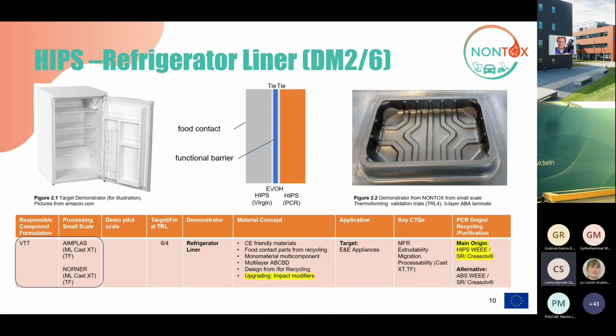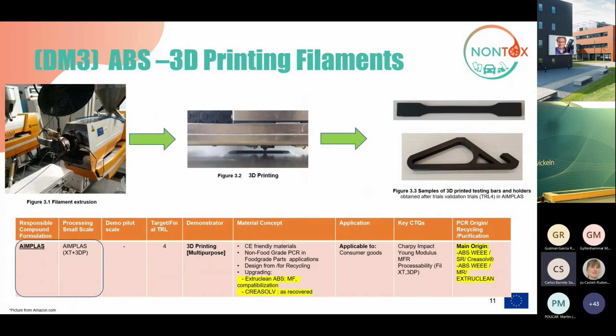That was an attempt to come to this refrigerator liner, where the idea was developing laminates for food contact on one side with virgin material, having a functional barrier layer, and HIPS PCR from CreaSolv on the other side. We managed to come to the extrusion of these asymmetric laminates, coming to a good conclusion on the good processability of HIPS PCR, even in this asymmetric application. The focus for the upgrading was, again, impact modifiers. And as I mentioned, the material was HIPS from CreaSolv.